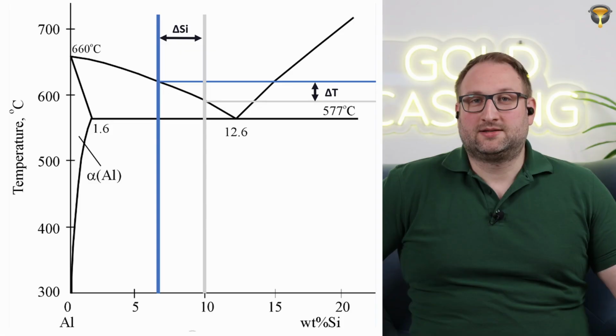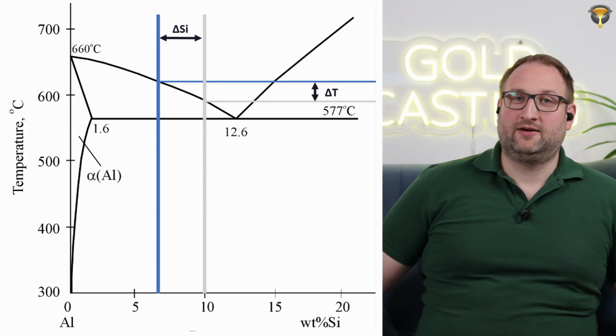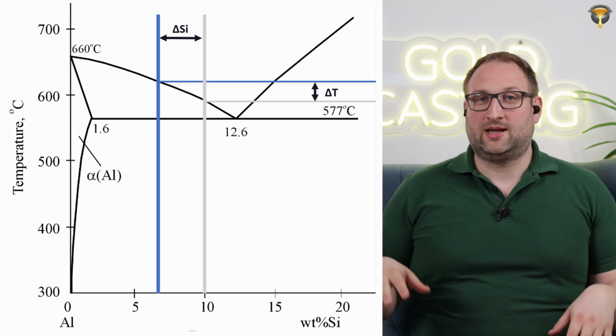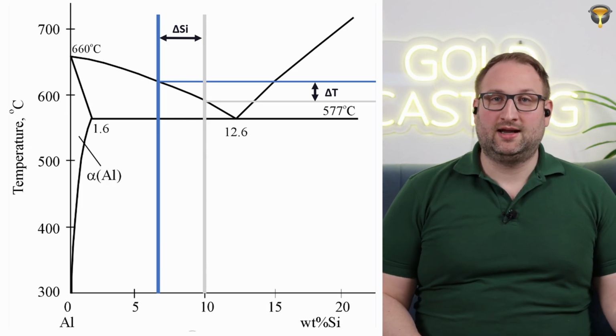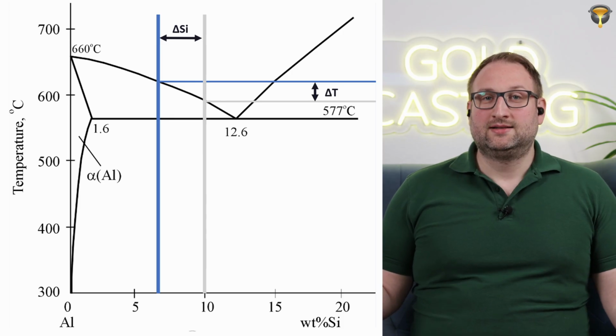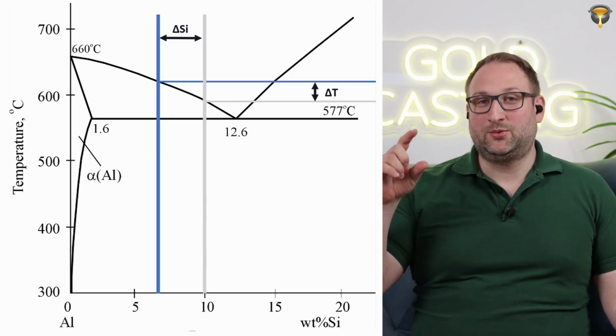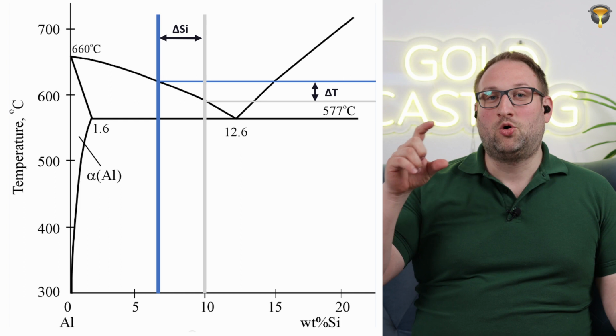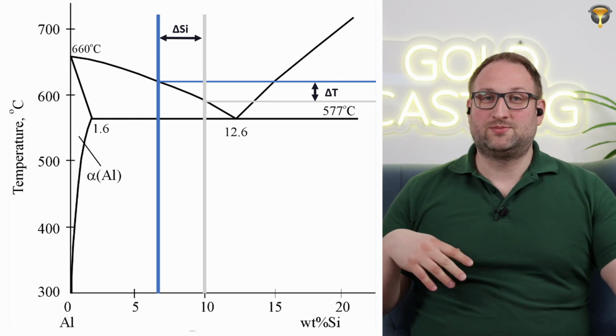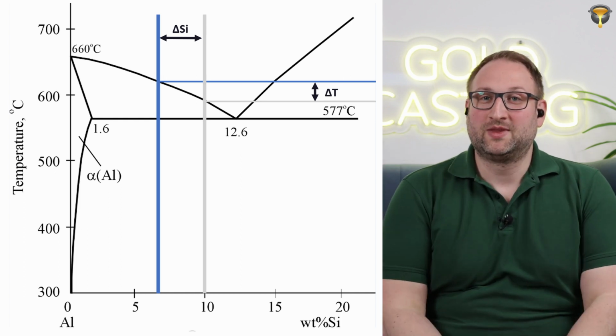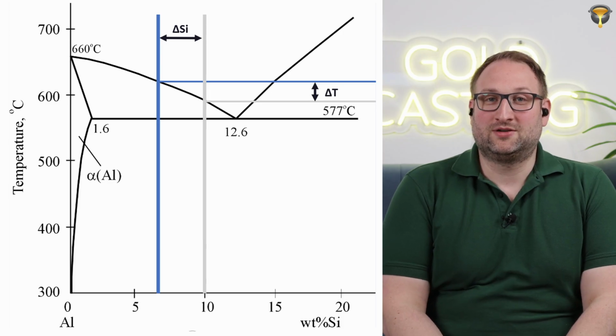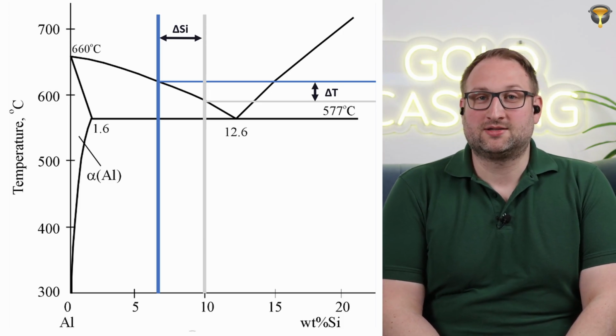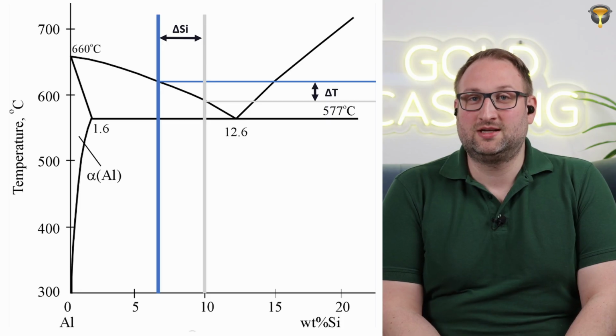If you're running in a laboratory, you have one batch of metal and cast that same batch every day, you don't see the issues. But when you have a series production running and have these small changes in the chemical composition, 0.5% silicon more there, next day a bit less, then suddenly your liquidus temperature changes more than your temperature between 20% or 40% solid fraction. And we can see the difference in the part very quickly. You cannot see it in the process, in the slurry making, but you see it in the part.